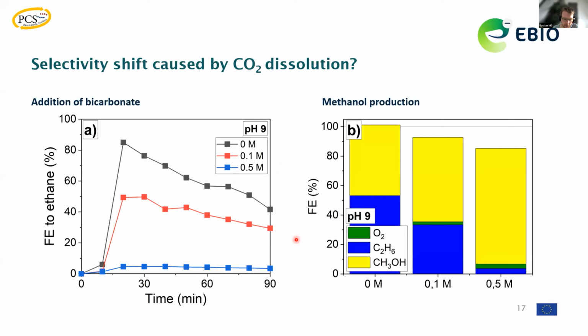So, which I haven't shown here, of course, if we use supporting electrolytes, Kolbe oxidation is inhibited depending on the type of addition you actually use. But the important part here, I think, is that it all still goes hand in hand with what you have also shown in your presentation, when methanol formation is basically being facilitated, right? Because you also talked about additional supporting electrolytes that are used in these cases. And I think what we're adding here is just a supporting electrolyte that influences the double layer structure in a way that it's actually facilitating methanol production.